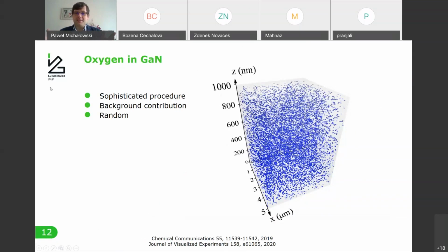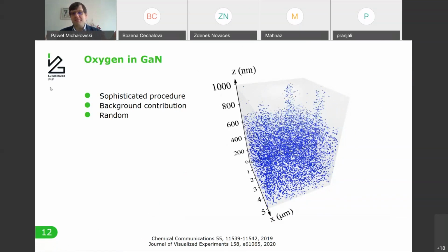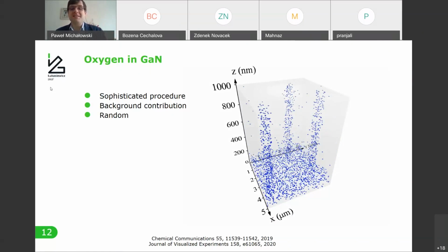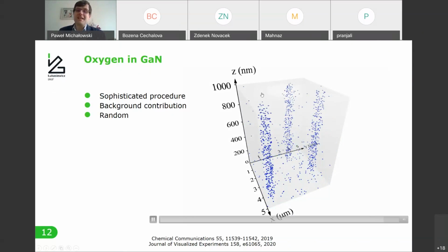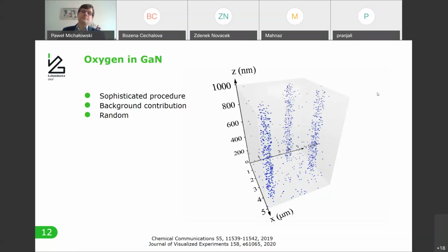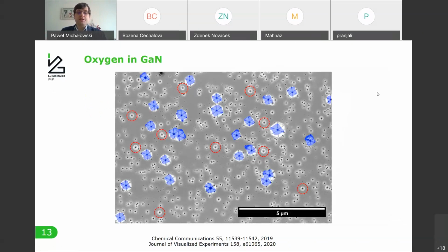As you can see, when we start to eliminate 95% of them, it turns out that the oxygen is not uniformly distributed as it may seem at the beginning. Once again, we can see very clear pillar-like structures. The oxygen is agglomerated along some very narrow lines. Here, we combine the SIMS analysis with SEM pictures. We superimposed the SIMS results, these blue pixels, on the chemically etched gallium nitride material.